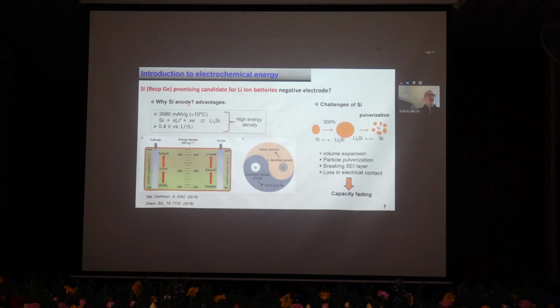So why does silicon have a very good advantage? Because the principle is a bit different than graphite. With silicon, the lithium is not going in between graphene sheets, for instance. It's creating an alloy with silicon. So during the lithiation, we create some LixSi, and we can have almost 4 lithium atoms per atom of silicon, giving a very high capacity compared to the carbon. The problem relies then also on this alloying, because when you make such an alloy, you have a 300 to 400% volume expansion of the silicon, which leads to particle pulverization during the use of silicon, and this enormous volume change creates a very short cycle life.